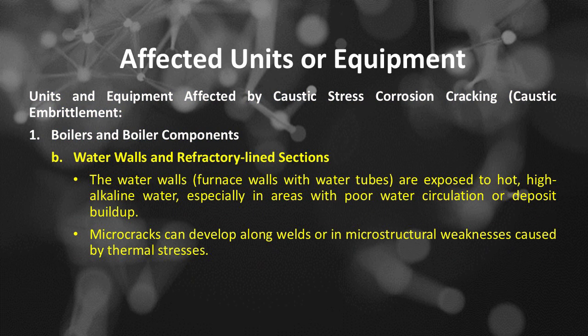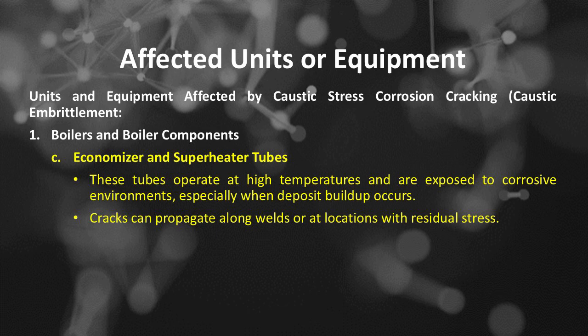Number B, water walls and refractory-lined sections. The water walls, furnace walls with water tubes, are exposed to hot, high-alkaline water, especially in areas with poor water circulation or deposit buildup. Microcracks can develop along welds or in microstructural weaknesses caused by thermal stresses. Boiler component number C, economizer and superheater tubes. These tubes operate at high temperatures and are exposed to corrosive environments, especially when deposit buildup occurs. Cracks can propagate along welds or at locations with residual stress.